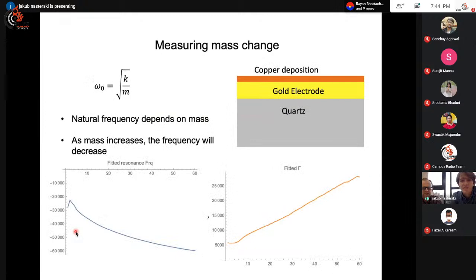But what we can do instead is do this deposition on a quartz crystal, and while the deposition is happening, we can measure the frequency parameters of the quartz. So we can keep doing those frequency sweeps. We can keep fitting the vibration properties and see how the natural frequency and dissipation are changing. So the natural frequency, if you remember from this one, depends on mass. So with increasing mass, the frequency is expected to go down.